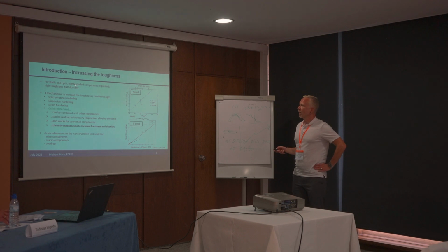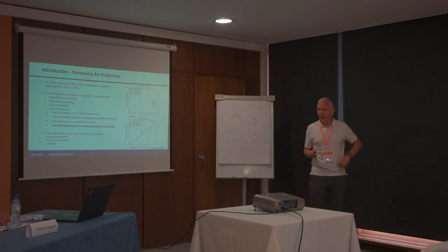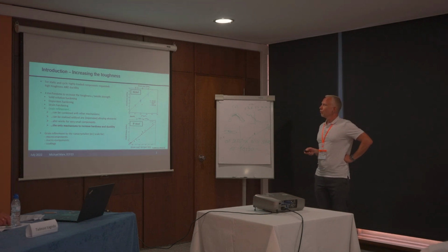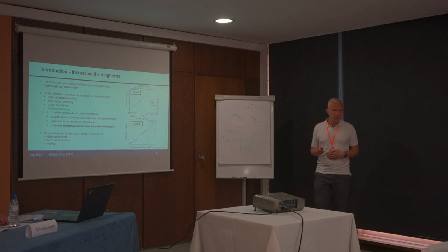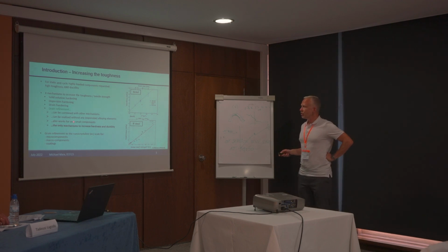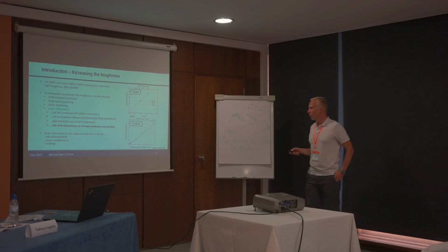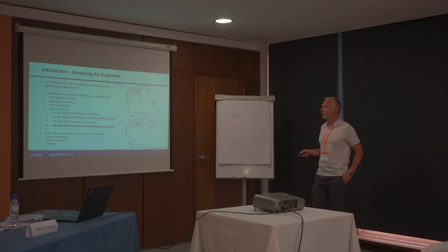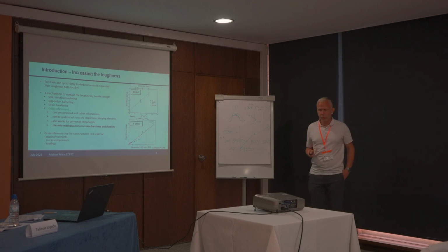For static and for cyclic loaded components, we need high toughness and high ductility, and you may know we have 4 mechanisms to increase toughness and tensile strength: solid solution hardening, dispersion hardening, strain hardening, and grain refinement. And the grain refinement has some advantages. It can be combined with the other mechanisms. It can also be realized without any expensive alloying elements. It also works for very small components, and it's the only mechanism to increase hardness and ductility.